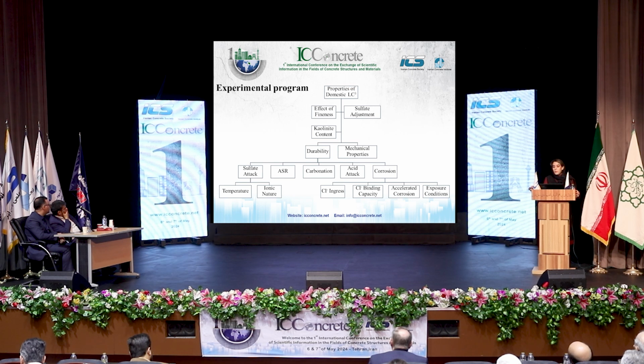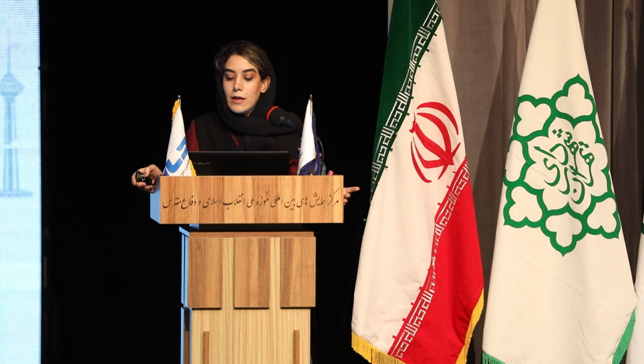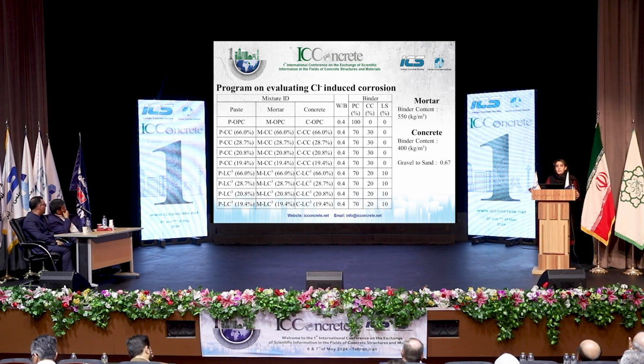Here is our team's experimental program. Me and Dr. Farnaz planned to analyze the properties of domestic LC3 considering the effect of fineness, sulfate adjustment, and kaolin content in the structures, and we carried out many tests with our colleagues, who were MS students, and some of them PhD students. The durability was evaluated by considering sulfate attack, alkali-silica reaction, carbonation, acid attack, and corrosion. We prepared paste, mortar, and concrete samples and considered 9 different mixture proportions. Among these 9, we have a control mixture, 4 binary mixtures, and 4 LC3 mixtures.